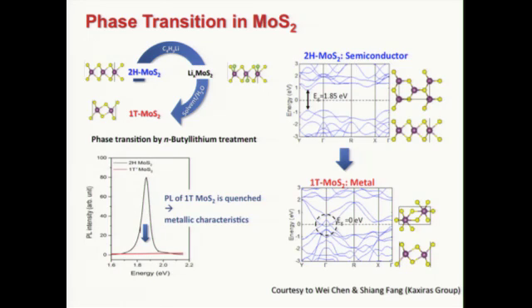The thing is that when we heavily dope molybdenum disulfide, the semiconducting configuration is not stable anymore. So it naturally undergoes this phase transition. It goes to the metallic one. Now, theoretically, if more than 80% of MoS2 is basically doped, even when we remove the dopant, it remains in its metallic phase because there is a potential barrier between them. It needs enough thermal energy to overcome the barrier. So that's stable at room temperature.